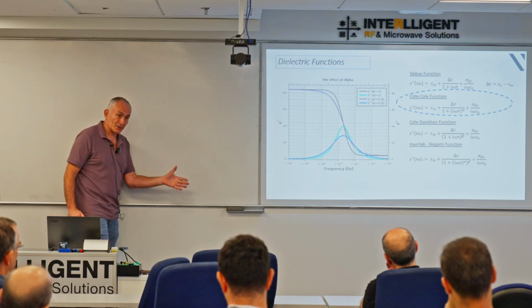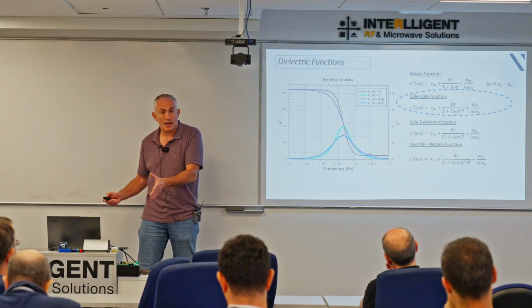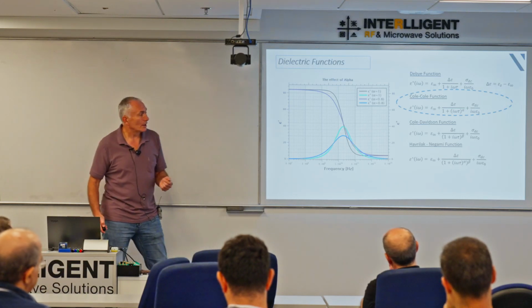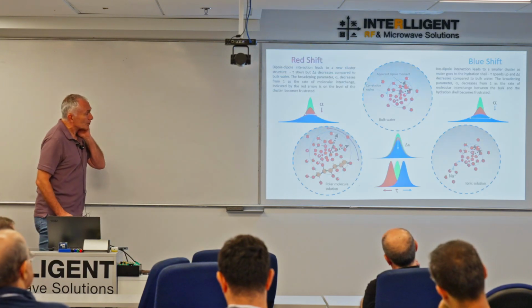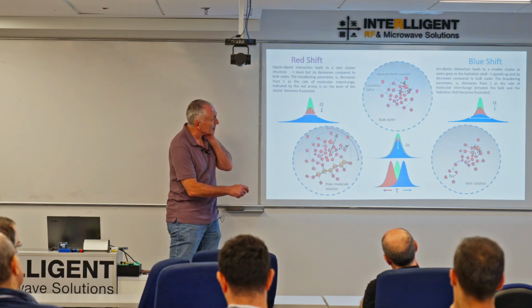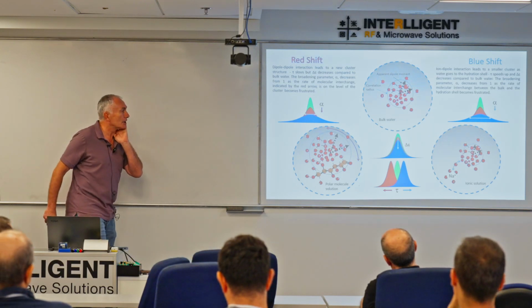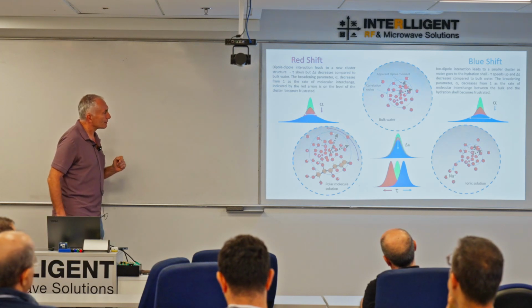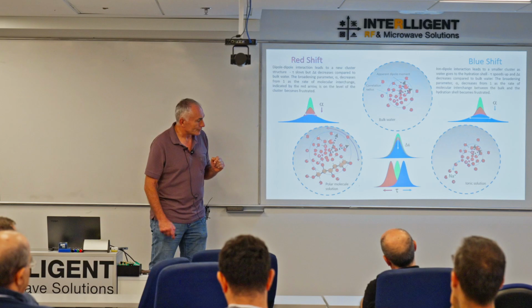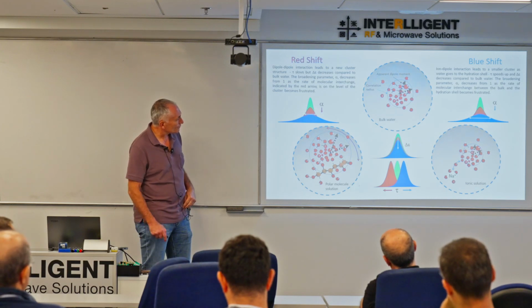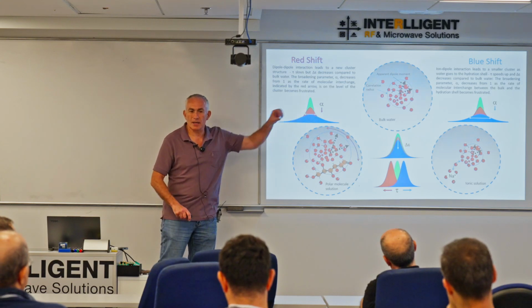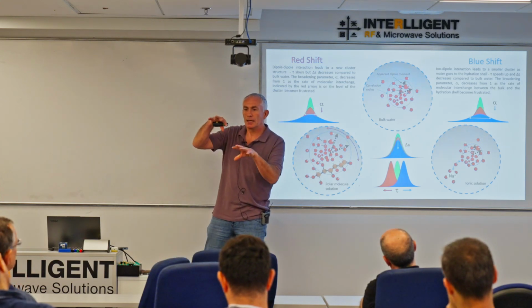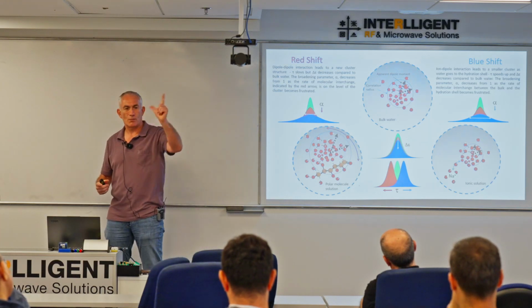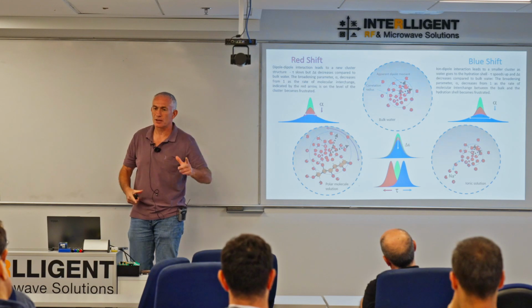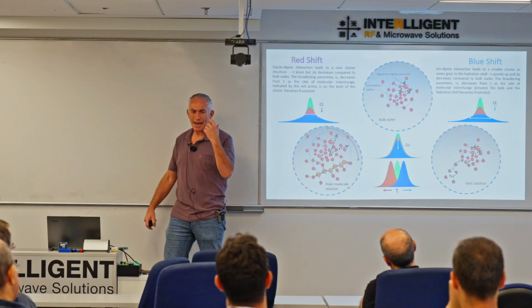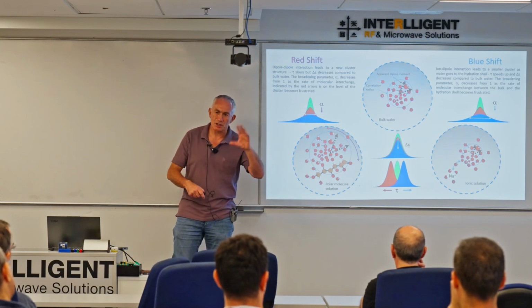Well, it depends what you're measuring. You will have noticed until now I've barely talked about what I measure. So, you can see some strange things happening depending on what you measure. This is taken from a review article that Yuri Feldman and I wrote, which I forgot to put the citation up for. So, if I'm measuring water, and here I've made a schematic of what water looks like, and I look into the molecular dynamics of water, it's not just molecules twisting around like this. They actually interact with each other, and they act like a cluster. And what I actually see is an apparent dipole moment which shifts.